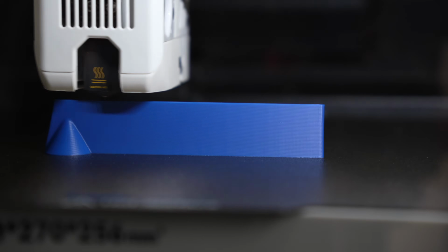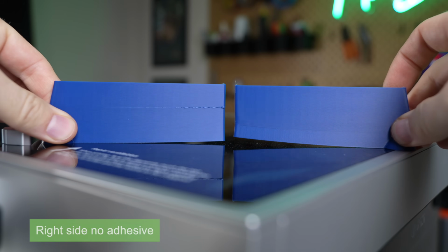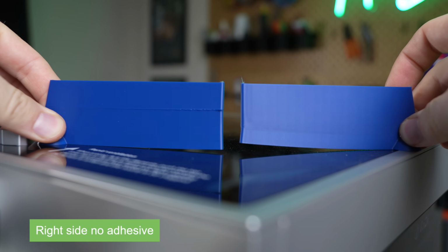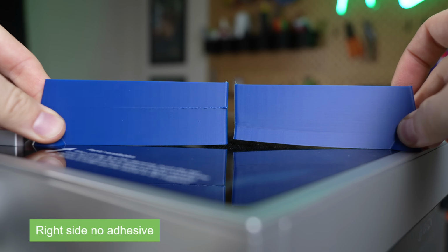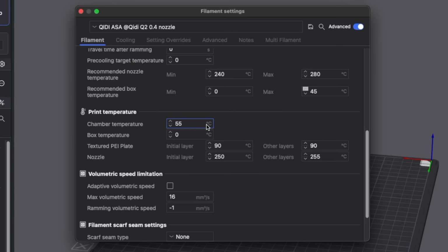The part with adhesive also warped, but didn't start until about 65 to 70% of the way through the print. If we put these two parts side by side, you can really see the difference between how much more the part without adhesive warped. Moving on to ASA.